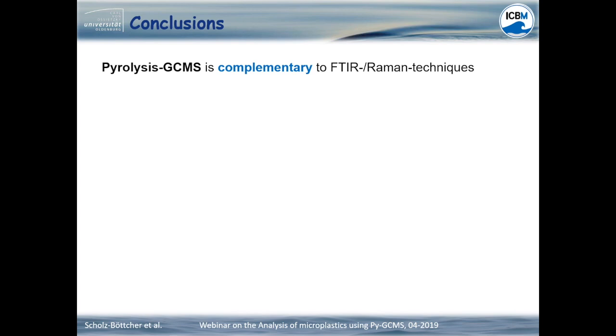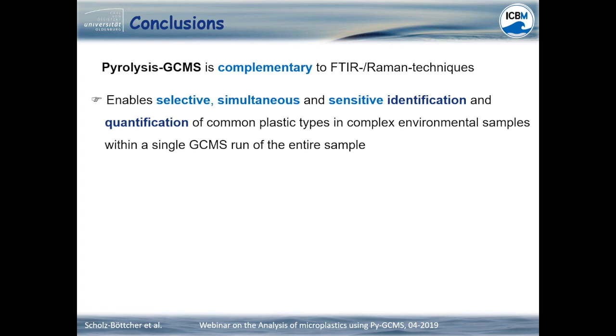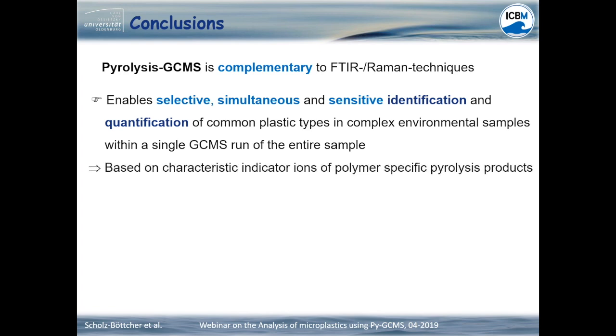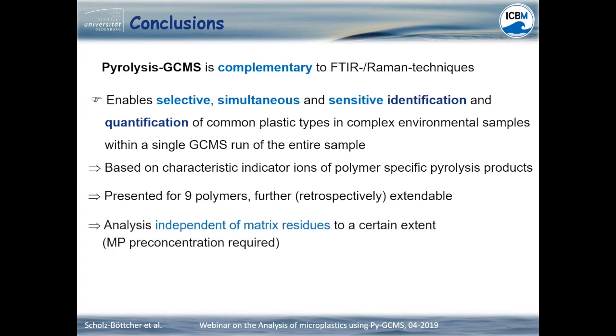To wrap up the presentation, we have seen that Pyrolysis-GC is complementary to FTIR and Raman techniques. It enables a selective, simultaneous, and sensitive identification and quantification of common plastic types in complex environmental samples within one single GCMS run of the entire sample. It is based on characteristic indicator ions of polymer-specific pyrolysis products. It was presented for 9 polymers, and this could be further extended, even retrospectively. The analysis is independent of matrix residues to a certain extent, but microplastic pre-concentration from environmental samples is usually required, and we get mass-related microplastic quantification on a trace level.